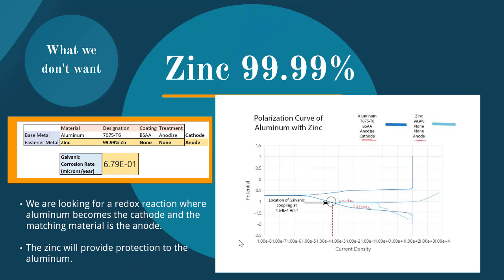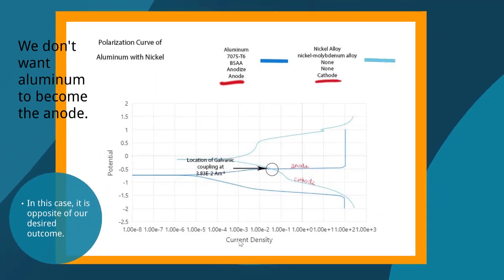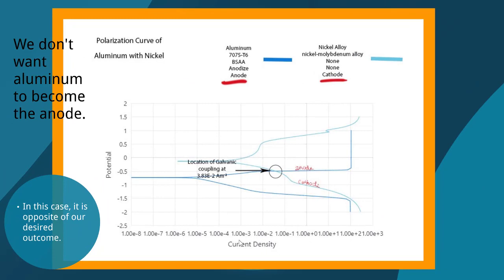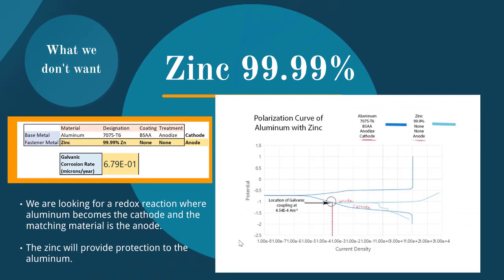Now, zinc is the best option because we are looking for a redox reaction where aluminum is the cathode and the fastening material is the anode. The anode acts as a protector of the aluminum. As you can see in the graph on the right, the cathodic protected side of aluminum crossing with the anodic active side of the zinc is at 4.54 e to the negative 4 amperes per meter squared. Now, what we don't want is for the aluminum to be on the more active side where it'll start to corrode on itself, as seen in this example in the chart when I matched it up with nickel.